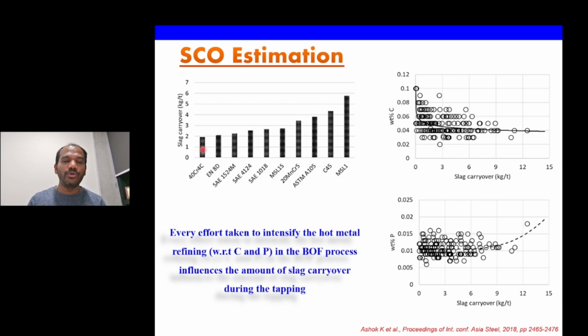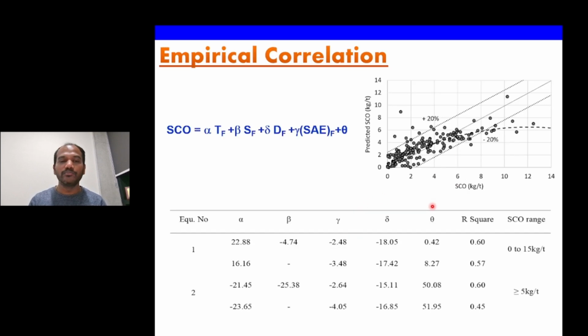But interestingly, if you note these grades, as you move from left to right in this direction, the end carbon and the end phosphorus are less. It means if the BOF practice involves the maximum removal of carbon and phosphorus, then basically you are ending up with more slag carryover. Here there are some indications given with weight percent carbon and weight percent phosphorus. These are all some obvious conclusions that we got from the results.